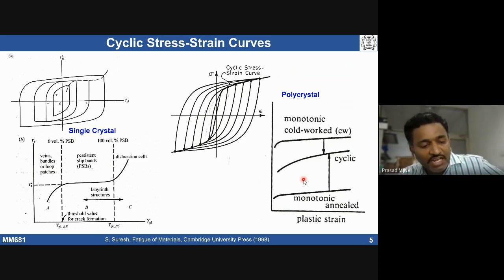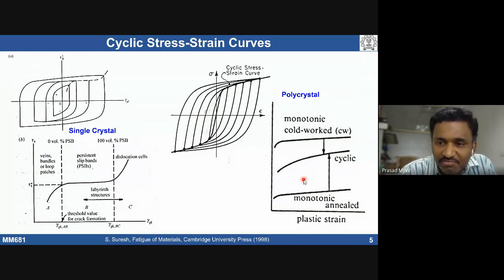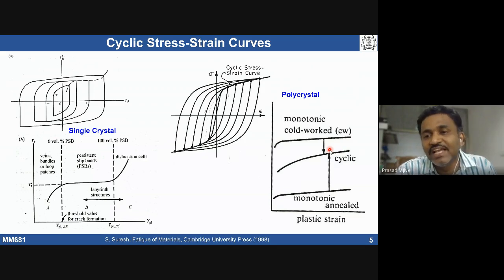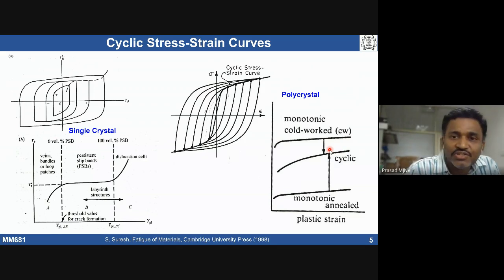If I take an annealed material which can get strain hardened, that can undergo cyclic hardening. In case of cold work material, it already has enough dislocations, so those can undergo cyclic softening because of annihilation of the defects. Persistent slip bands can form very easily, which can lead to reduced strength under cyclic loading conditions. So this is for polycrystal.